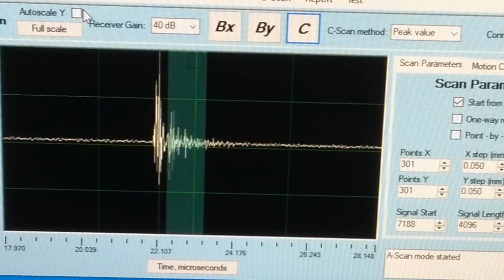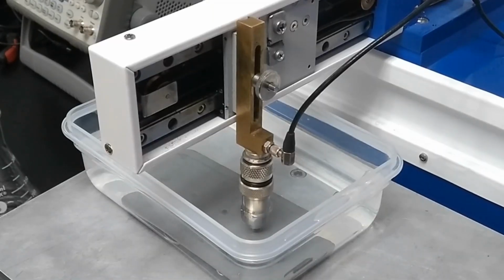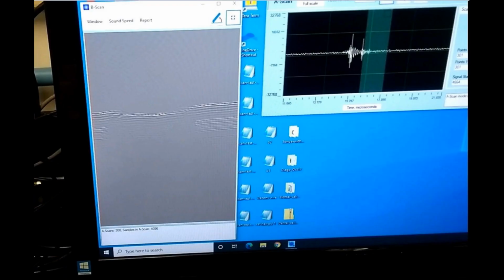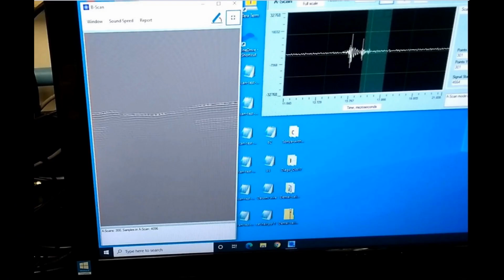For the B scan, the transducer will only need to move along a single axis. The software will generate a grayscale B scan image. The white areas represent positive amplitudes, the black areas represent negative amplitudes, and the gray area represents zero amplitude. The first surface reflection appears as a horizontal line consisting of alternating black and white colors. The line dips down towards the middle. This is caused by a physical indentation in the sample created by heat and pressure during the spot welding process.